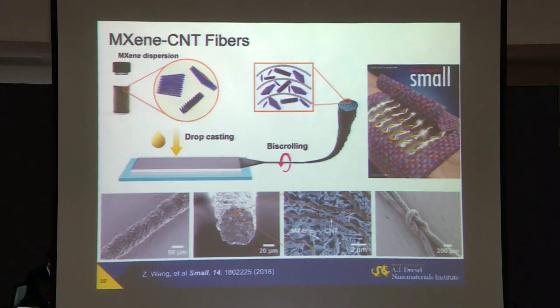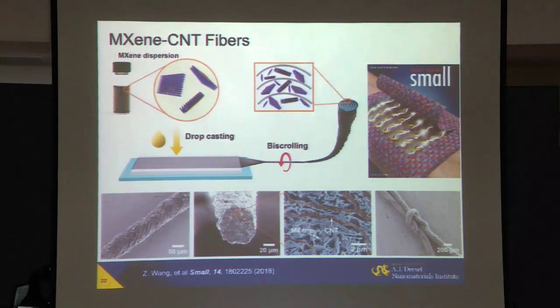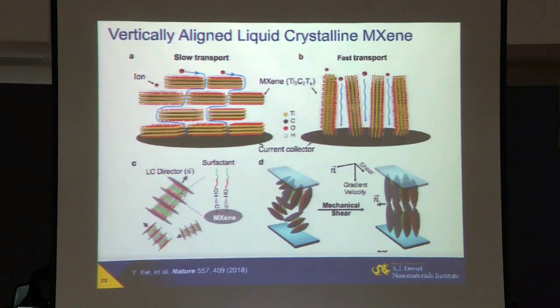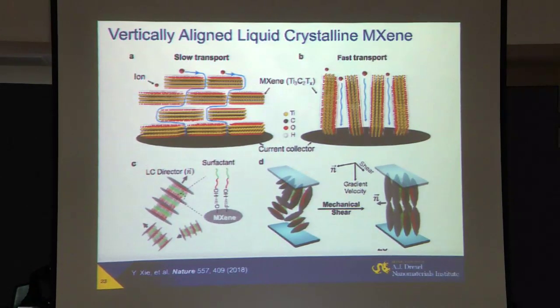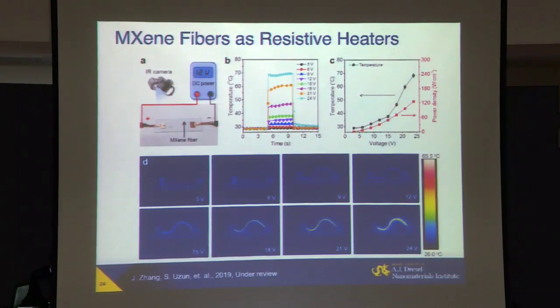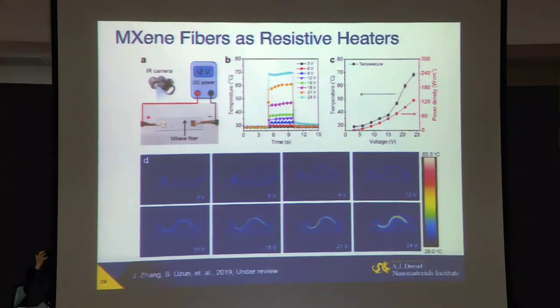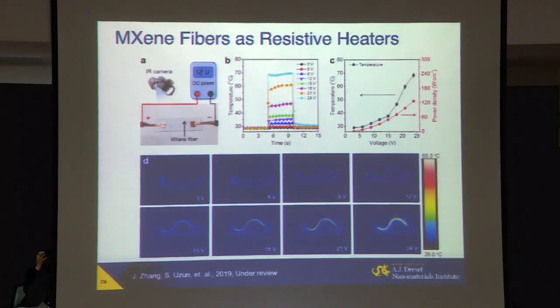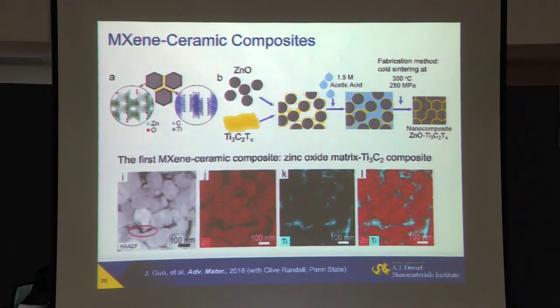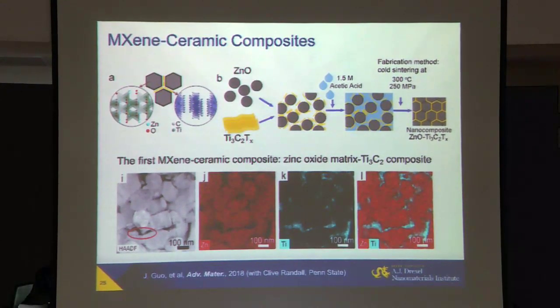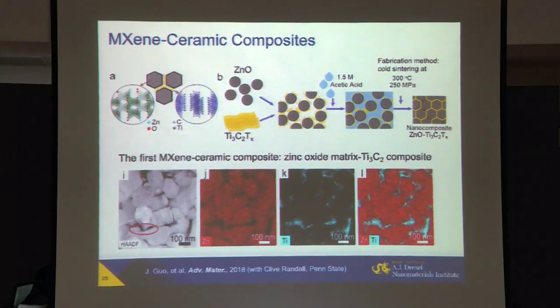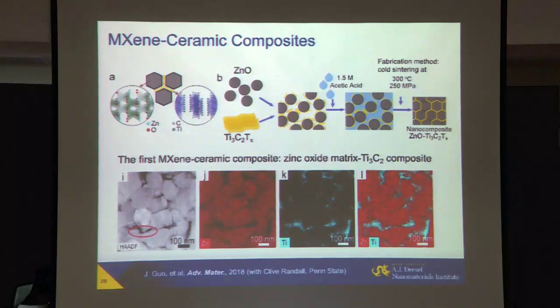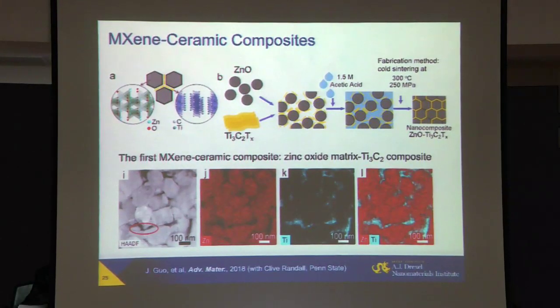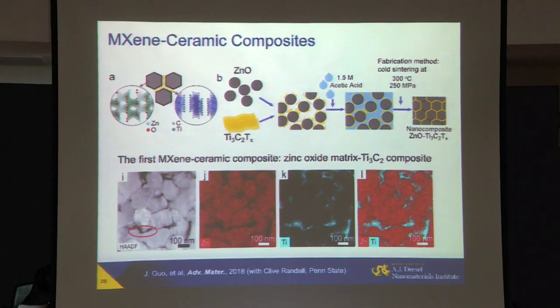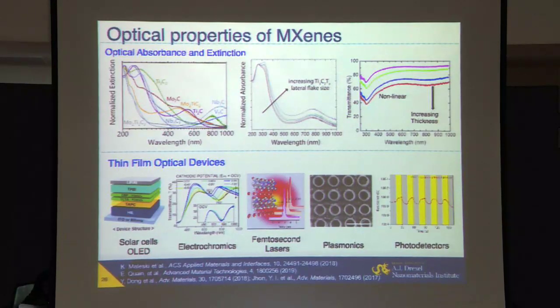And of course, you can process them now just like any other solution processed materials. You can make fibers, for example, those are scrolled fibers. We can make liquid crystalline structures and align them in different ways like liquid crystals. We can make fibers, actually draw fibers, and use them as heating elements, just like metal wires. We can incorporate these materials in polymer matrix, ceramic matrix, or metal matrix composites, use them as reinforcement, or in case of ceramic, also conducting additives, which not only increases mechanical properties, but also adds conductivity to the materials here.